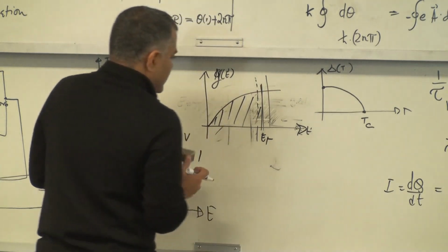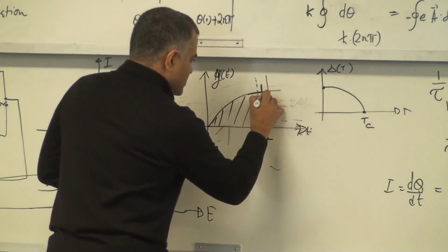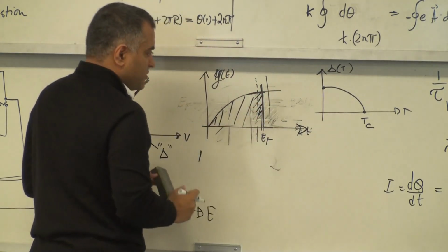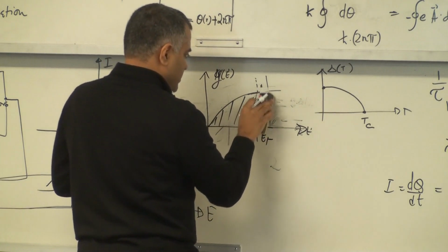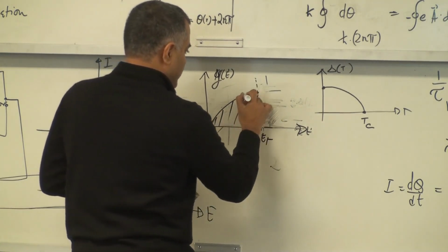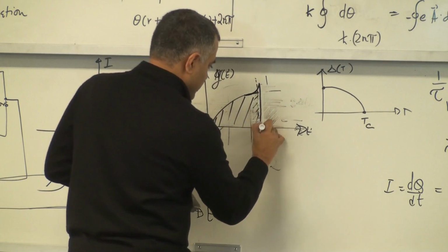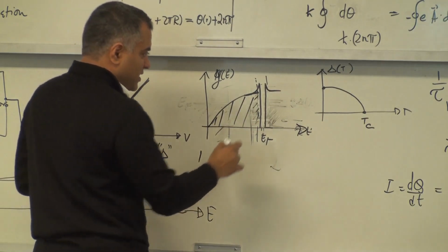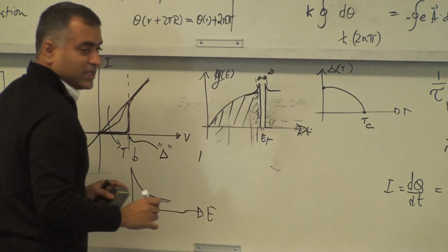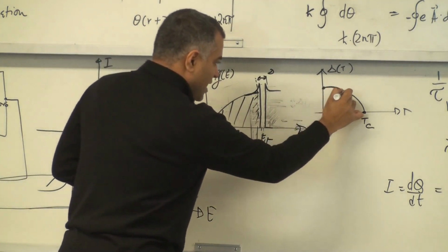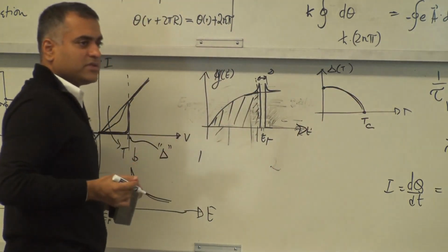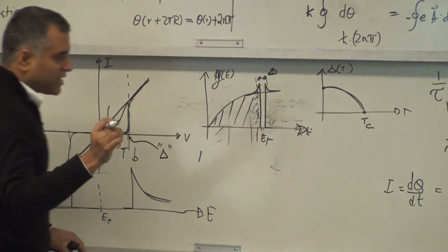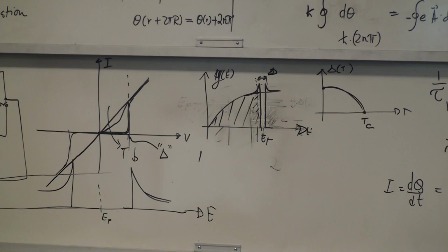So what has happened here is the density of states, instead of being just like this, this would be the typical density in occupied and unoccupied states at the Fermi level, has been changed because of the superconducting transition in a very interesting way. It has become something like this, okay, and then there's a gap here. And that's what is being measured right there, and this is the superconducting gap, delta. And as you change the temperature, this gap will close, and finally it will become a normal metal again. So this is a temperature-dependent gap opening that is directly measurable using tunneling transport.